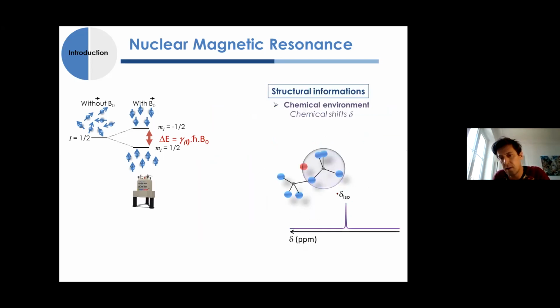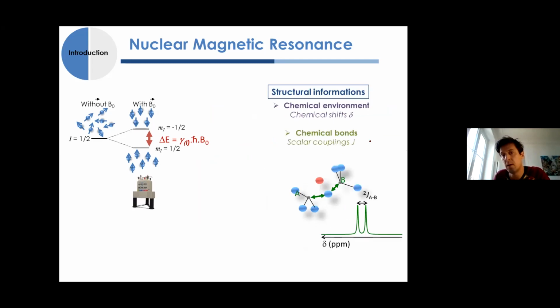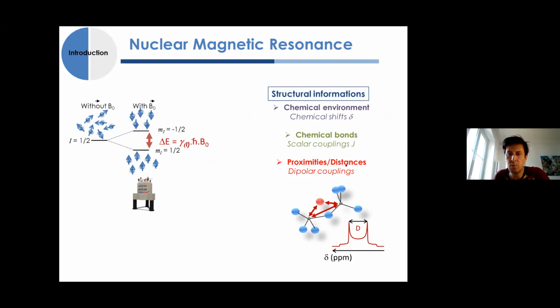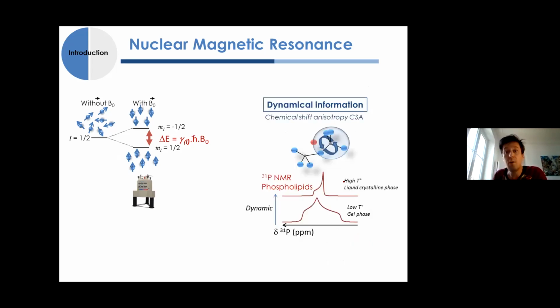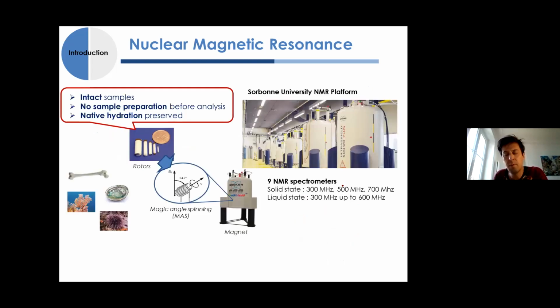You have access directly, as I said, to the chemical shift, and the chemical shift is directly related to the chemical environment. You also have access to the chemical bonds through scalar couplings, in the case of liquid NMR, not really solid. You also have access to information about proximities and distances through the use of dipolar couplings. But you also have access to some dynamical information by looking at the averaging of some anisotropic interactions—here the chemical shift interaction through the dynamics. So you have really a lot of tools, a lot of different parameters and interactions that give you access to specific information.